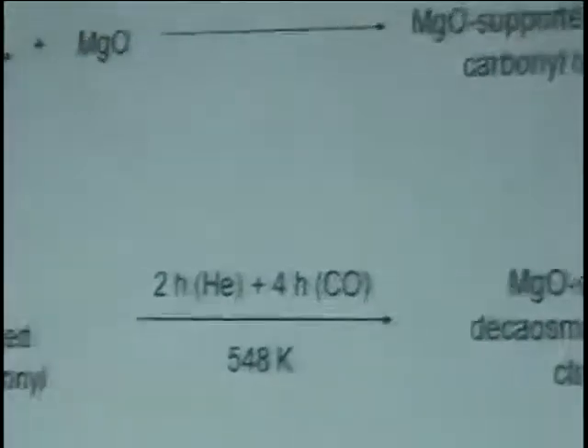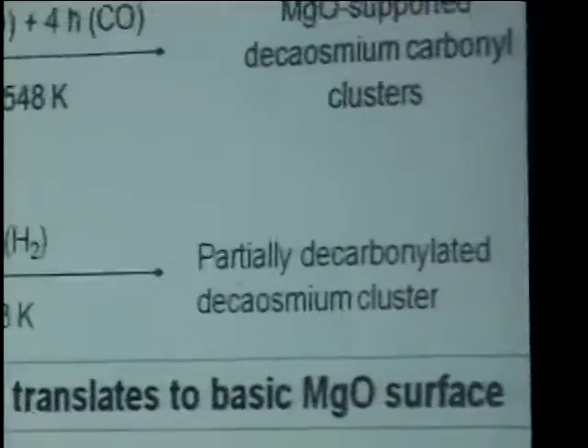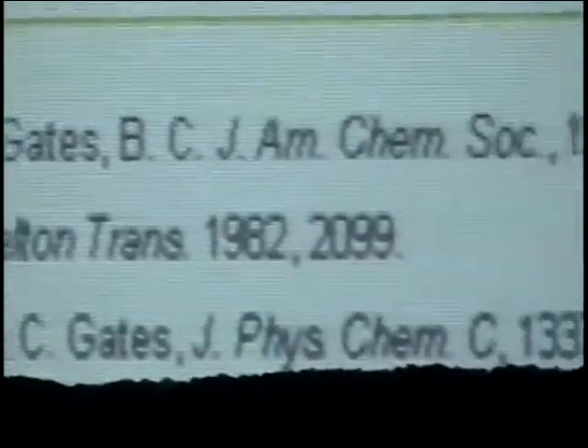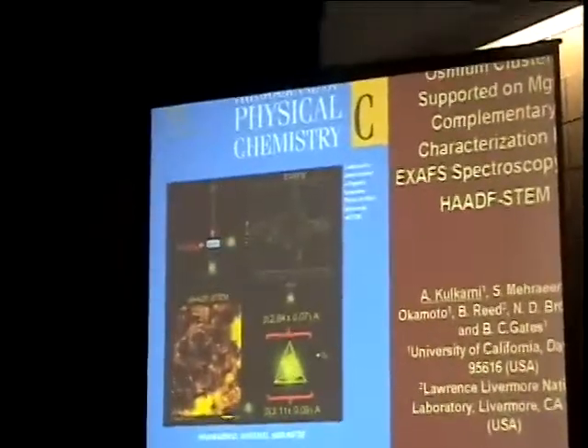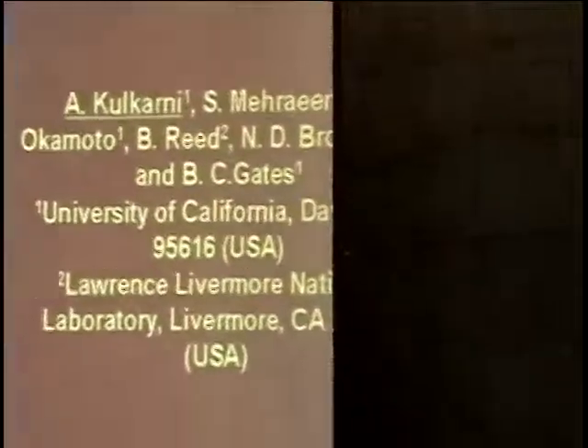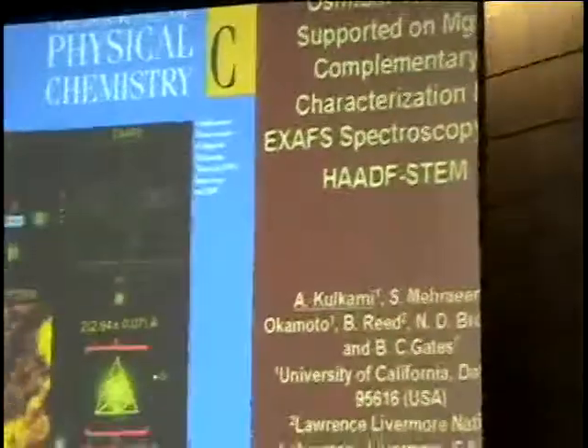So we can start with the triosmium on MgO, and we can treat it to fragment, and then we can treat in CO at higher temperature. And the temperatures are going up here to reductively carbonylate to make larger clusters. So we can go from the triangular frame to the deca-osmium frame. I'll be brief about that, but we've used the microscopy to characterize what are predominantly the deca-osmium clusters. We did the synthesis to try to get as high a yield as possible. You can get 65% or so yield of the deca-osmium on the support.